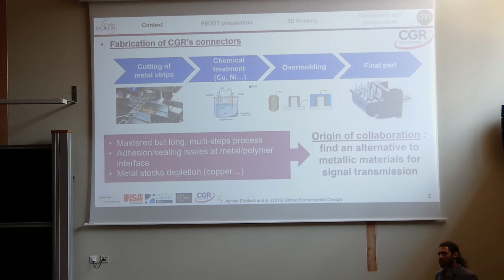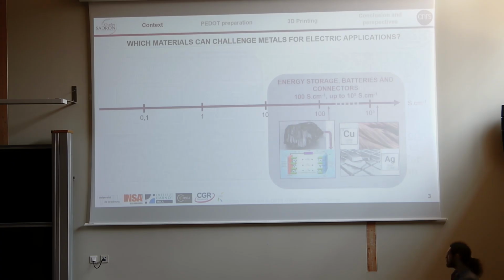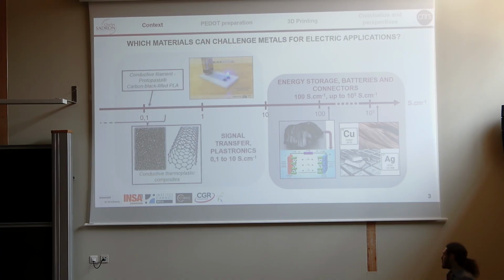And also we are in the context where the metal natural stocks are running out. So it was interesting to find an alternative to metallic materials for signal transmission. But so what conductivity are we talking about? Right now, we are mostly using metals whose conductivity reach up to 10 to the power of 5 Siemens per centimeter. But it's been found that when you go down to between 0.1 and 10 Siemens per centimeter, you are conductive enough to make signal transfer, plastronics, and so on. And this is notably the case for conductive thermoplastic composites, which is the kind of material we are interested in.